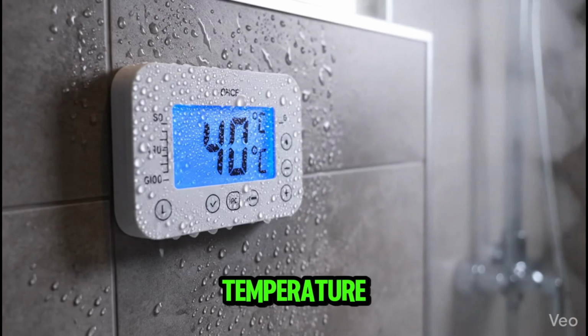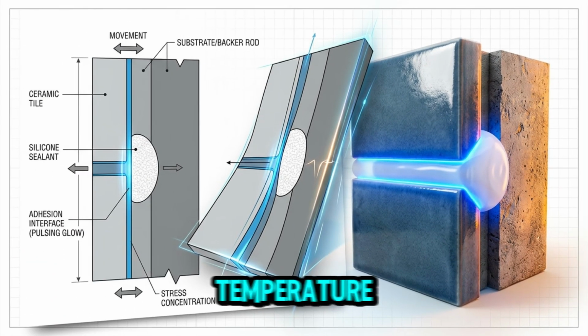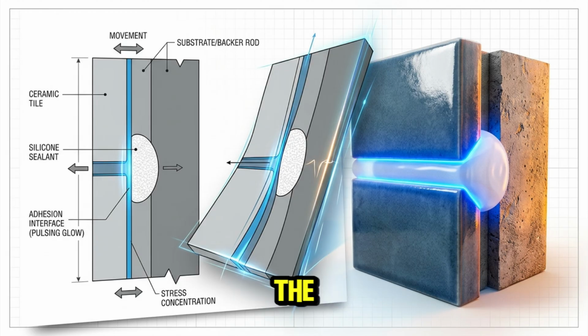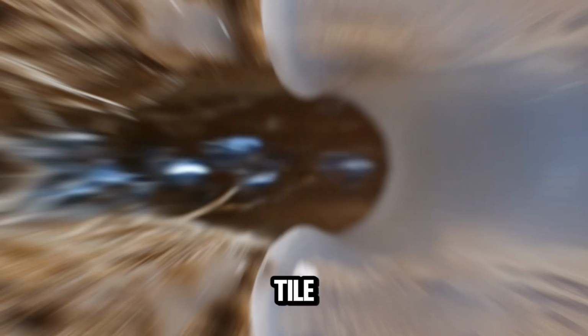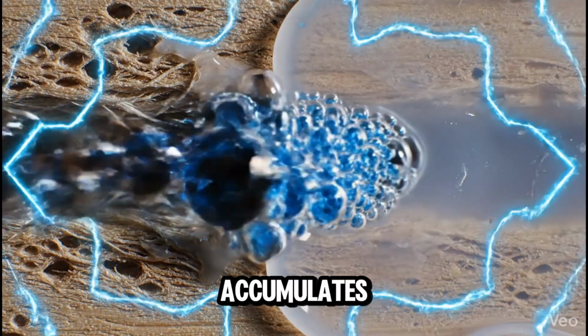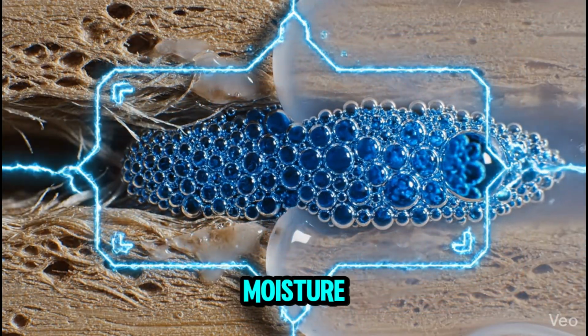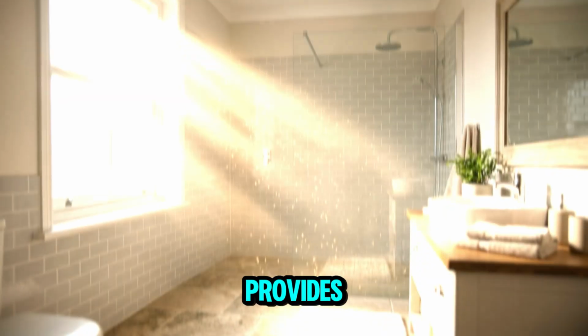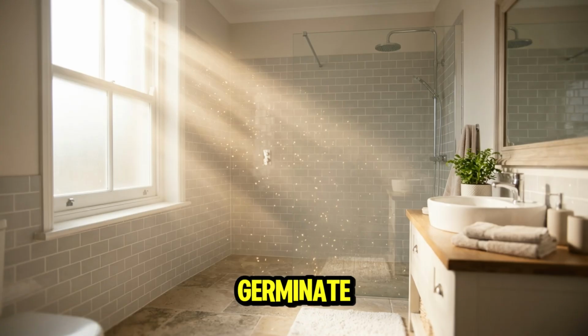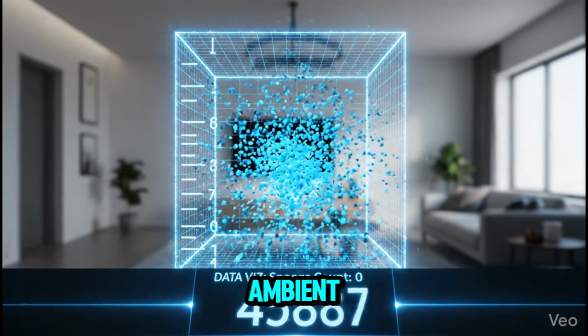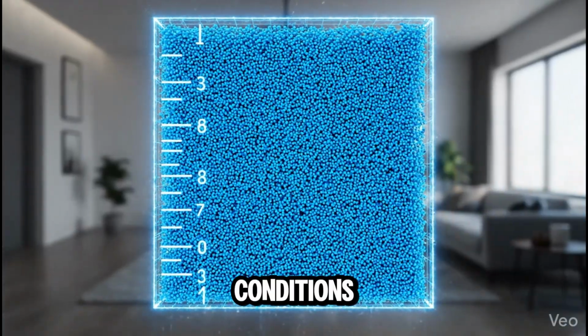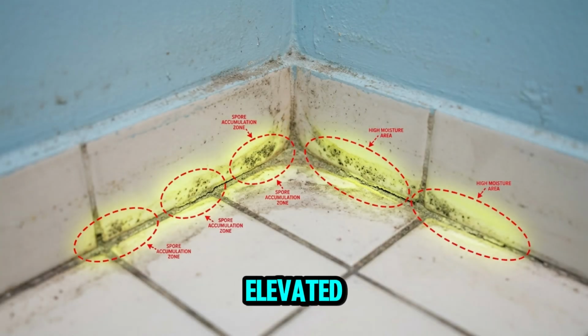In a bathroom, where temperature cycling between hot shower conditions and ambient room temperature creates repeated condensation cycles, the interface between the silicone and the substrate, the tile, the tub surround, the window frame, accumulates moisture at the microscopic level. That moisture, trapped at the substrate interface, provides the water activity that fungal spores require to germinate. The spores themselves come from normal room air. Every interior space has ambient fungal spore counts in the range of hundreds to thousands of spores per cubic meter under normal conditions. In a bathroom, those counts are elevated by moisture and organic material. The spores settle onto every surface, including silicone joints.